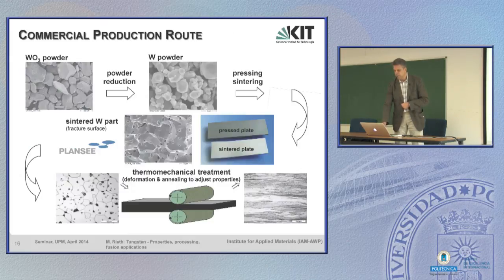Now let's quickly go through the production of tungsten. In industry it starts with tungsten ore or tungsten oxide powder, then that's reduced under hydrogen atmosphere at rather high temperatures, and then the result is pure tungsten powder. This is pressed, then it looks like that. After that it's sintered, it shrinks a little bit, then it looks like that. Thereafter it is thermomechanically treated, which means at various but rather high temperatures rolled or forged or whatever